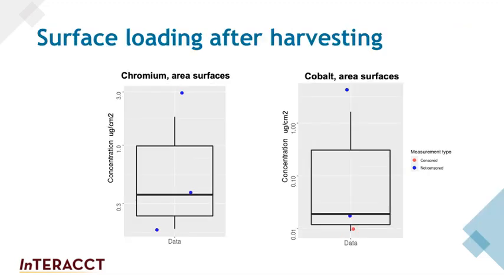We were also able to take a few wipe samples following harvesting. Here again, we have no surface limits to compare these results to, but you can see that in both cases they span at least an order of magnitude, if not more. This suggests that the potential for dermal exposures to these materials is quite variable, which is concerning as many of the components of the powders are sensitizers. This would be a good thing for health and safety professionals to look out for in this type of operation, and start off with a robust housekeeping and contaminant control strategy to try to avoid the buildup of powder on surfaces.